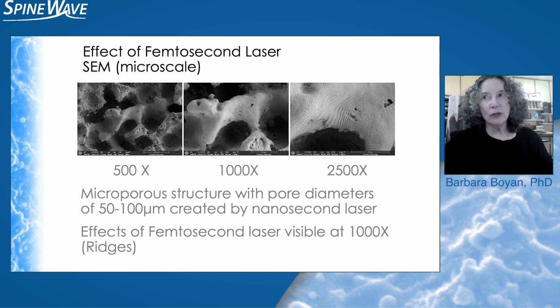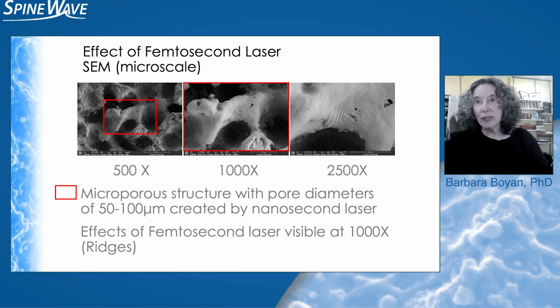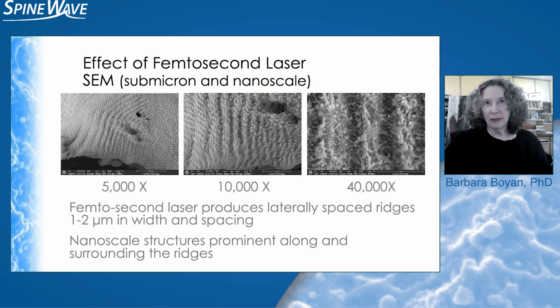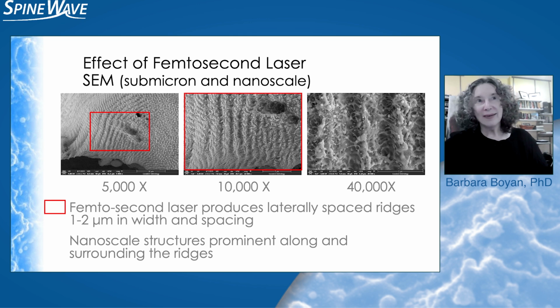Now, I really want you to focus in on this because I get excited. And if you're not excited, I can't work with you. You've got to get excited. Here we are looking at it in lower mag. We increase the mag and we can see these little ridges. And if we get even higher mag, here's all these laser ridges that are forming. And here we add the femto laser. And wow. Is that not wow? That is wow.